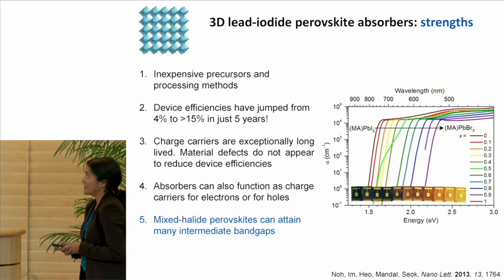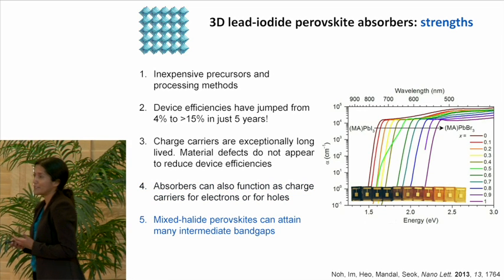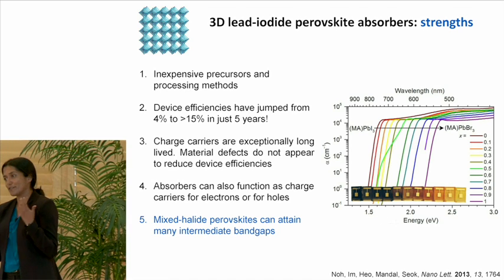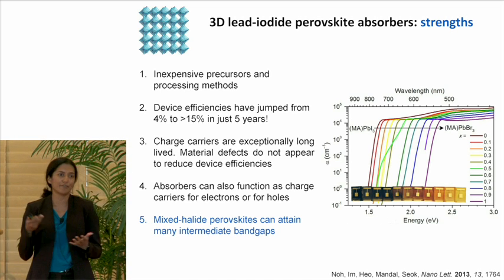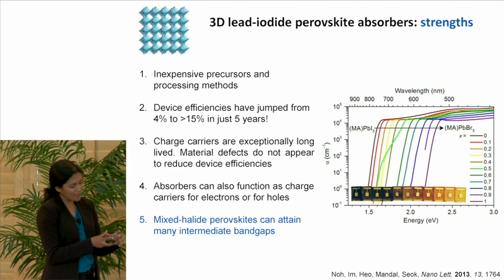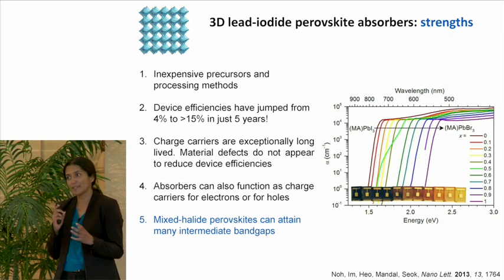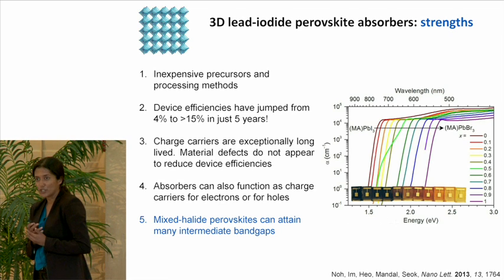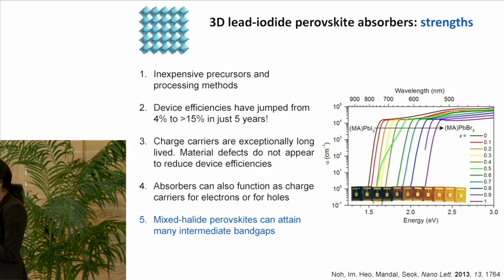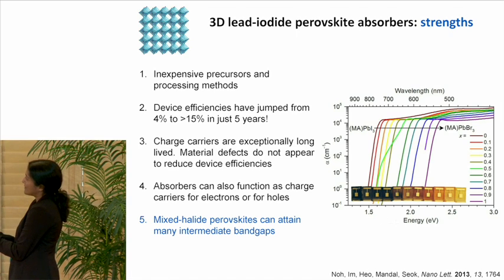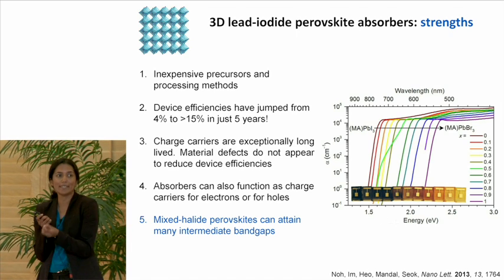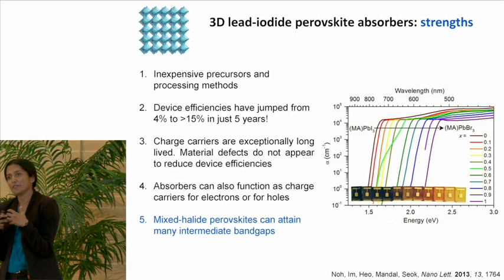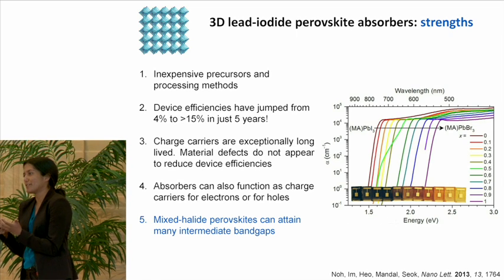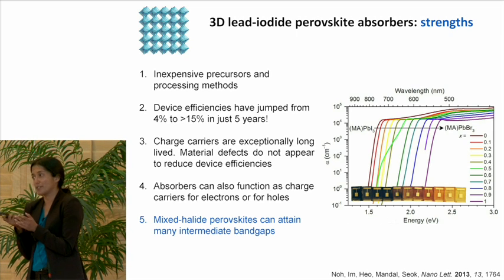And a very nice attribute of these materials is, again, just through solution state self-assembly, we can start adding different ions into the lattice. So we can start with the lead iodide lattice and then start doping it with bromide, and we can change the absorption energy of the material. And you can see that there's this nice increase in band gap as we start adding bromide into the lead iodide lattice. And being able to tune the band gap of the material is very interesting for lots of applications.